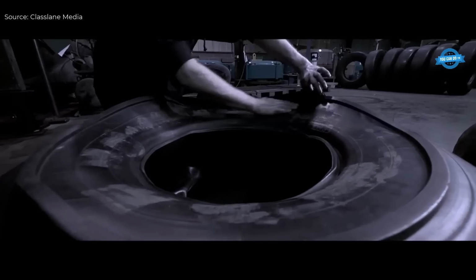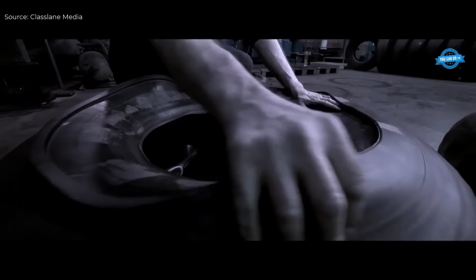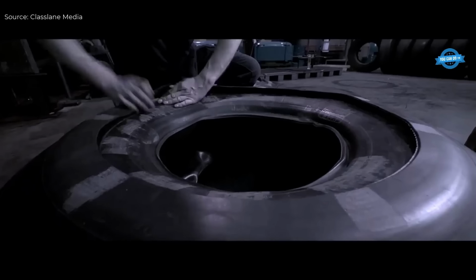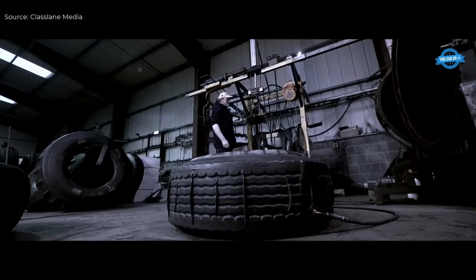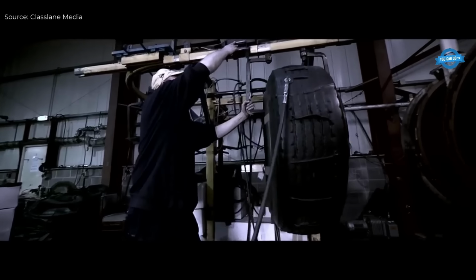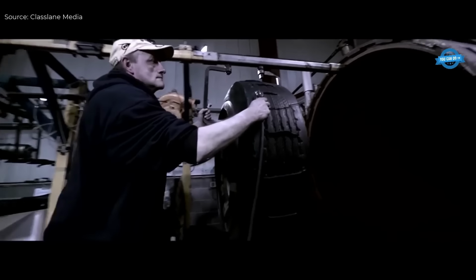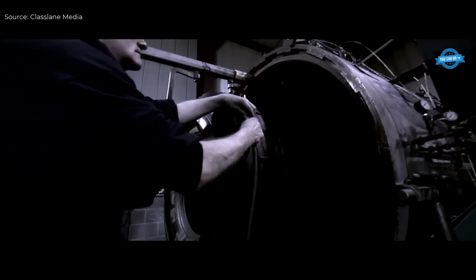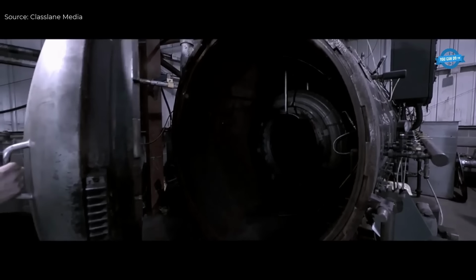The built tire is placed in a hot segmented mold within a curing press. It is heated to 150 degrees Celsius and inflated to 200 psi using an internal bladder. The heat, pressure, and curing time vulcanize the rubber, forming the required tread pattern and depth.